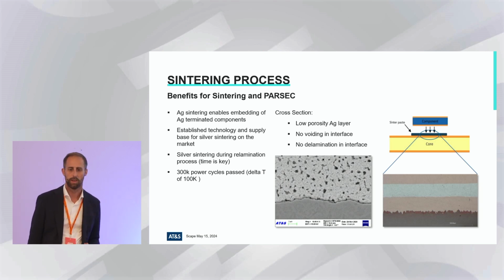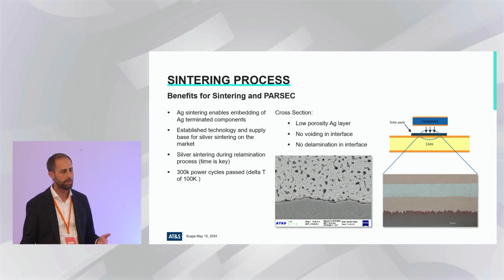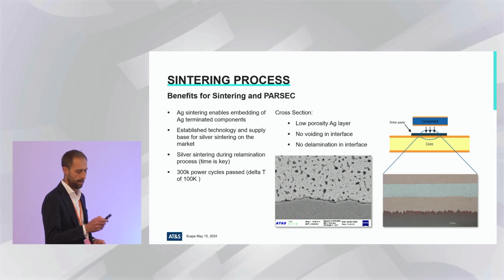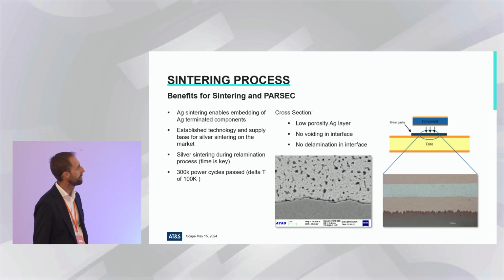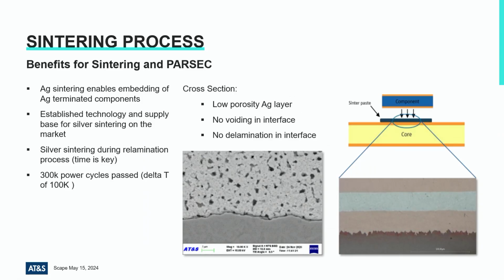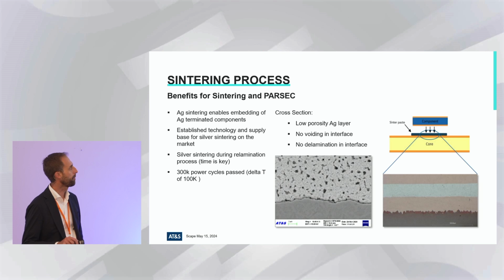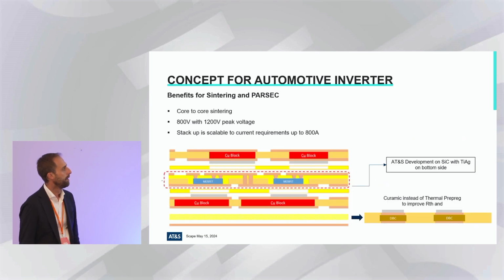And the second thing is we save cost, because when we do the lamination, we can also do the sintering together. So we have also done here more than 300,000 power cycles with a delta T of 100K. And as you can see also from the structure, it looks quite good. This I've shown also today already.